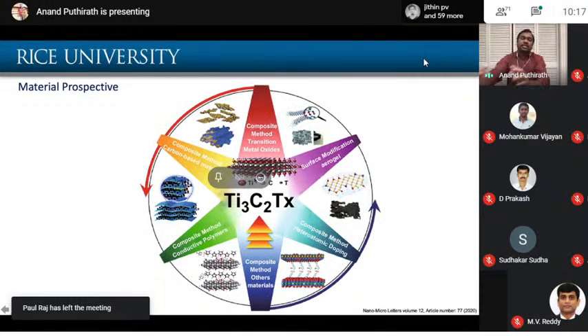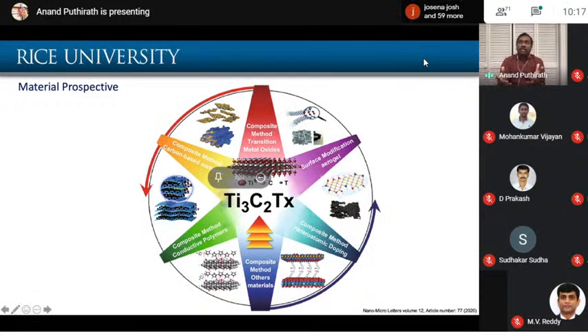And if you look at the behavior of a material that can be used as a capacitor, we don't want a fully metallic-like material, right? If it is metallic, the charge potentials at individual points are really less, because it will be an average thing, because in a highly conducting sample, it's a band-like charge distribution at the surface.